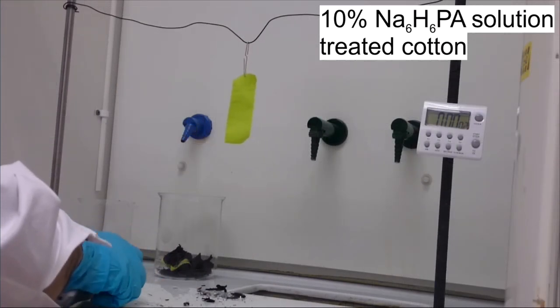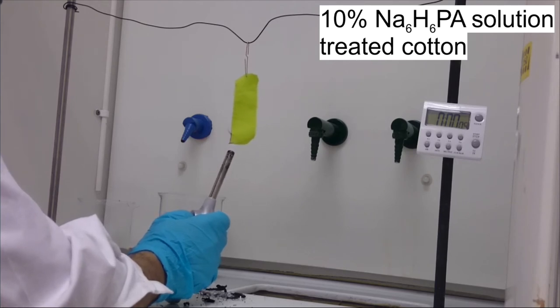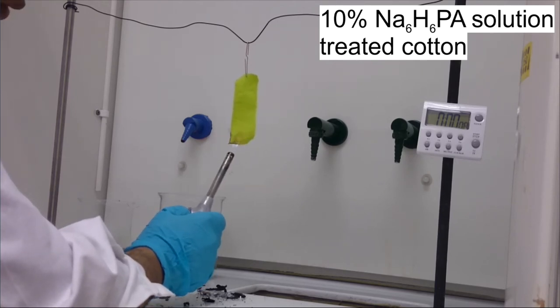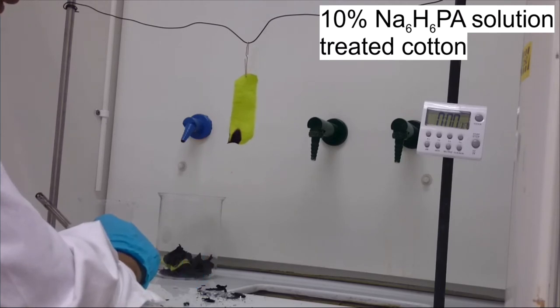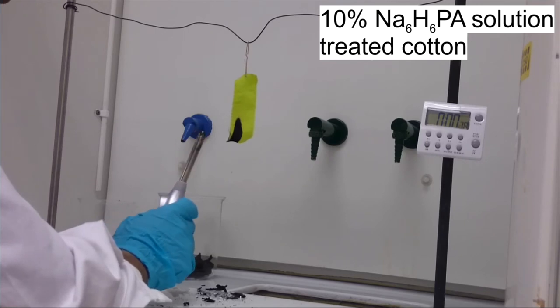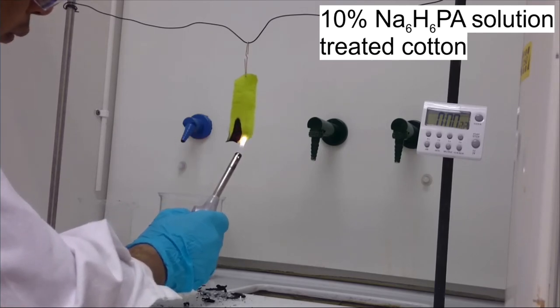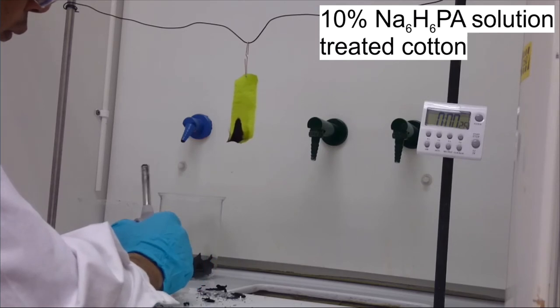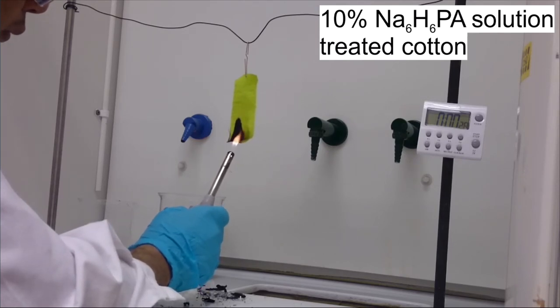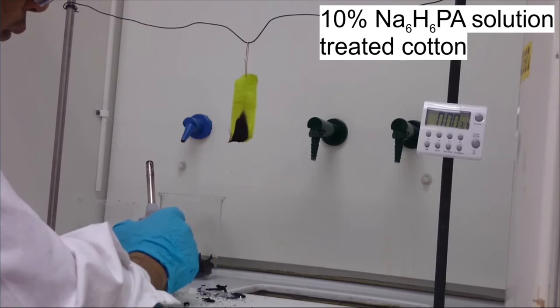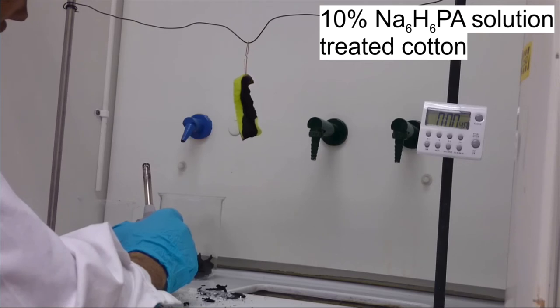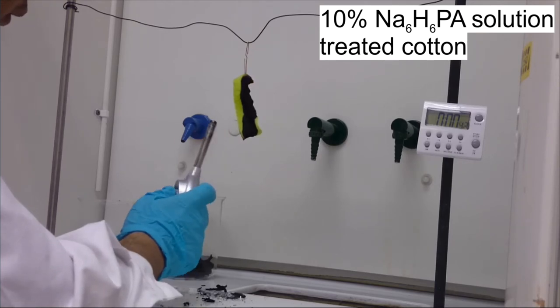Now we take a phytic acid sample. It's a sodium salt, actually, of phytic acid. I'm trying to put fire. No, it's only charring slowly, didn't catch fire. So I try a little more. Yes, again it is glowing, but there is no big flame. Now there is a very small flame.